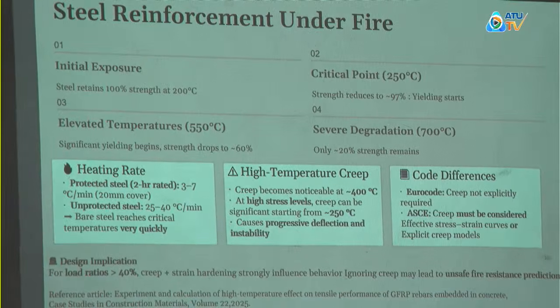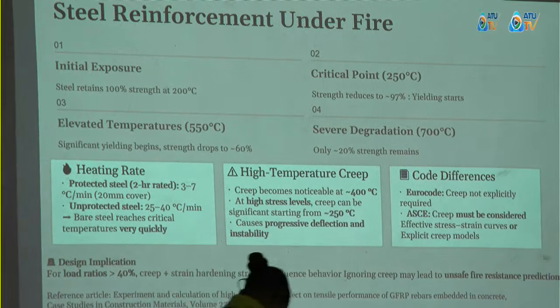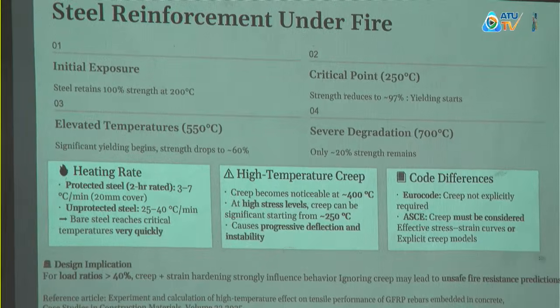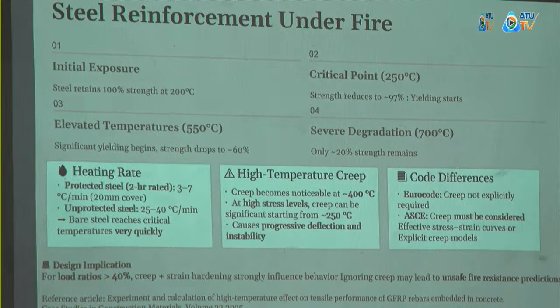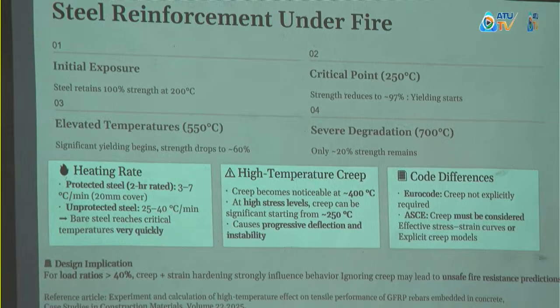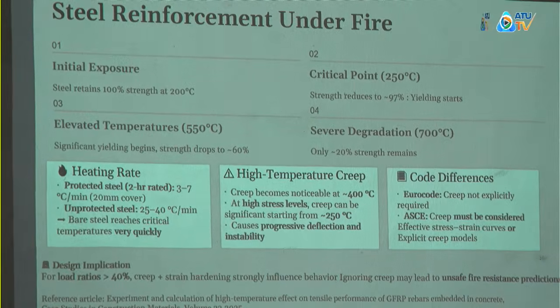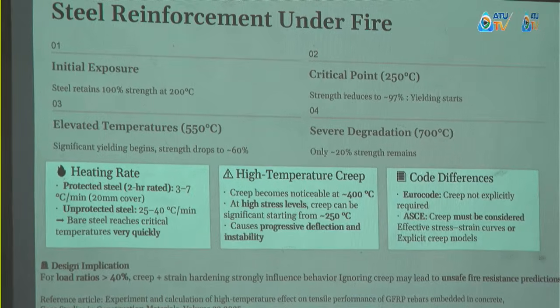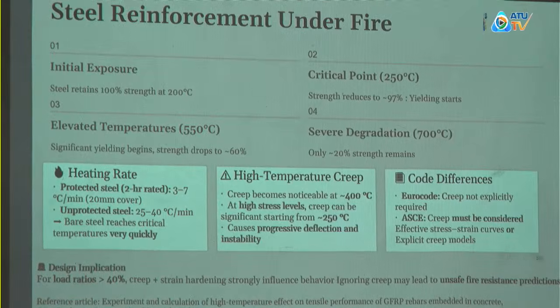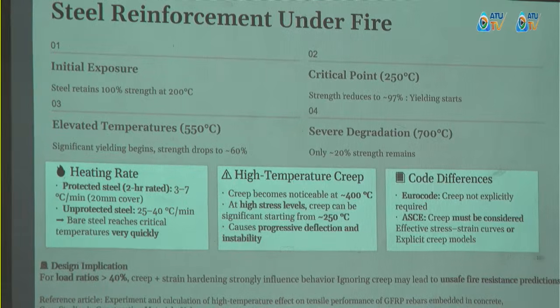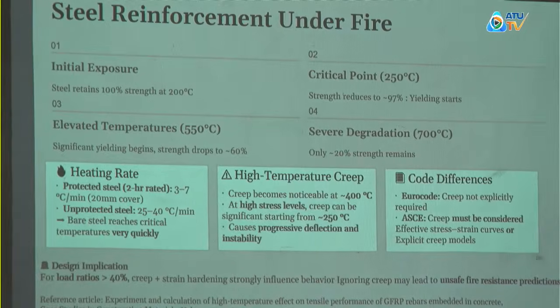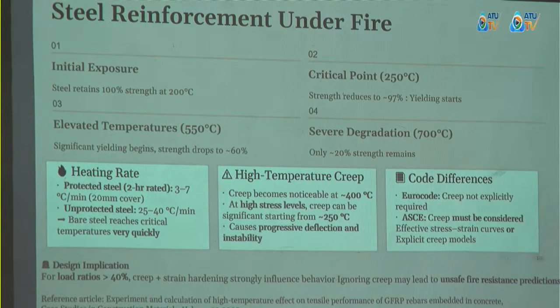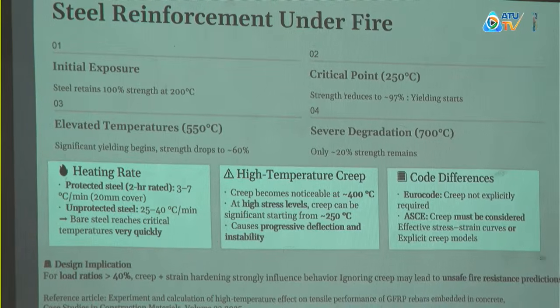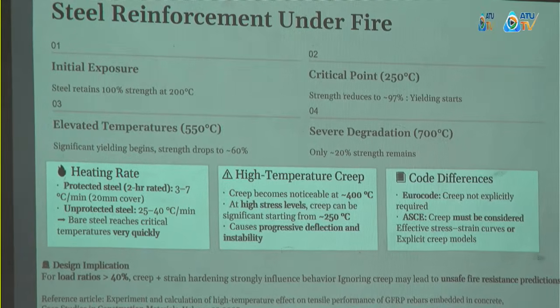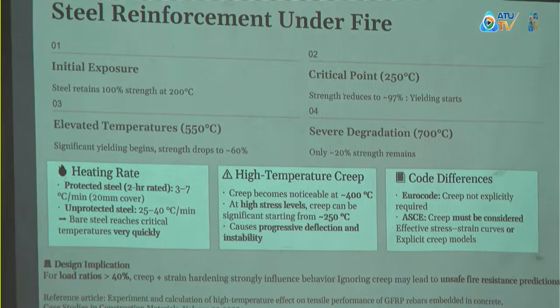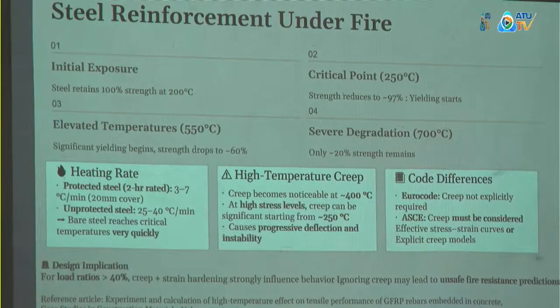And this is where steel's graph, according to the ASCE models and the Eurocode models, the yielding starts. And once the yielding starts and the temperatures continue to rise, steel's rate of yielding once exposed to fire is very high. So the failure is abrupt. The time for evacuation, which is 60 minutes, is usually for the concrete cover, that is for the design. But once the steel is exposed directly to the fire, steel no longer holds its ductility as much, because the graph of its loss of strength goes down drastically.